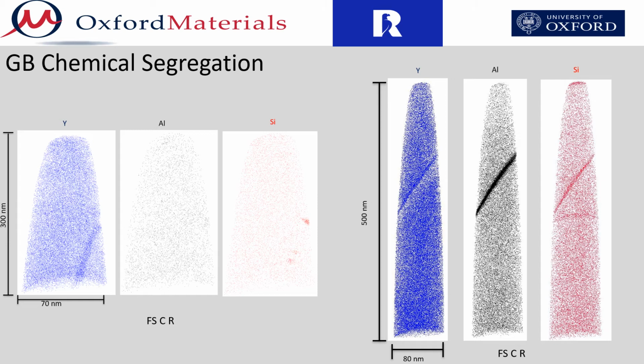The grain boundary on the left demonstrates significant yttrium segregation, no aluminium segregation, and 3 silicon clusters lying within the thickness of the boundary. The grain boundary on the right demonstrates significant segregation of yttrium, aluminium, and silicon. Although there is a variety of grain boundary types based upon segregation behavior between all the specimens studied, there seems to be no consistent difference between grain boundary segregation and type of sintering.